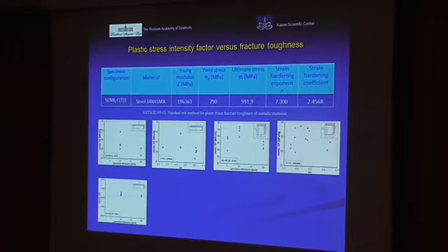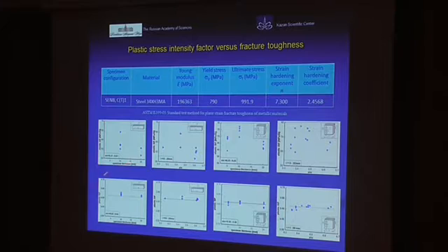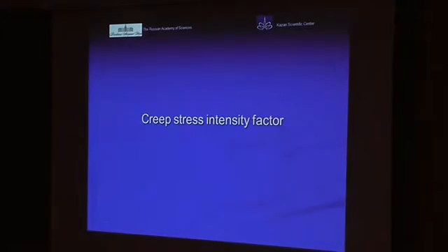But if you use the plastic stress intensity factor, you see that it is approximately constant for different specimen configurations, and is independent of specimen thickness and dimensionless crack length. From my point of view, that is the real property of the material, that is the real fracture resistance characteristic.